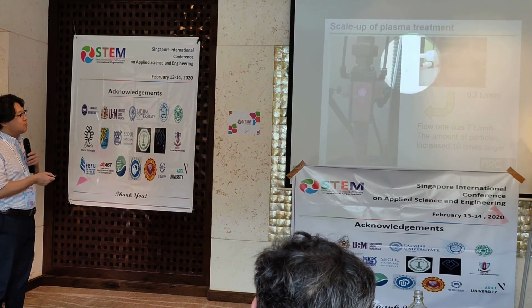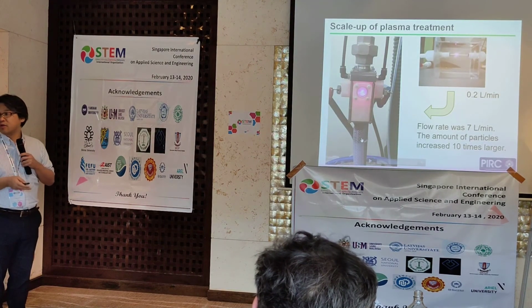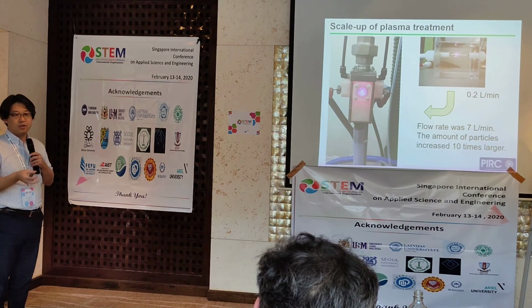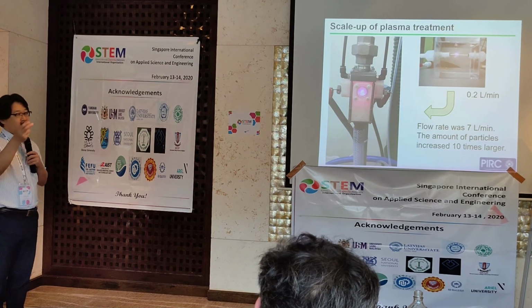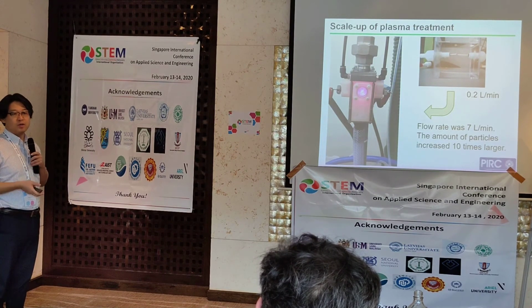Now we have improved to get a high amount of treated sample. This is a batch-scale, bigger-size plasma treatment. Now it is a flow system. This flow is around 7 liters per minute, including nanomaterial. A high flow rate and high volume of material is treated in this system.